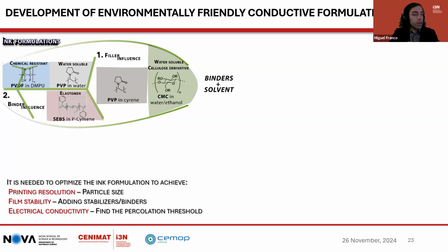Also, as an initial step for conductive inks, it is to find a percolation threshold that, in the case of graphene, tends to vary a lot in weight percentage when using different sorts of graphene, since its volume and density change a lot when changing different types of graphene.